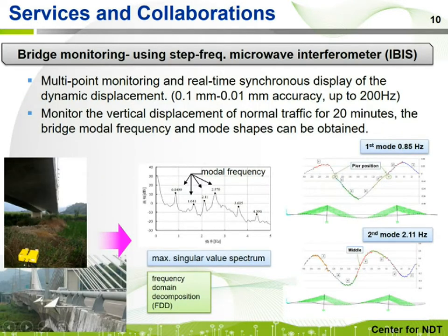An instrument called IBIS, which is a step frequency microwave interferometer, is used for bridge monitoring. IBIS can simultaneously measure the dynamic displacement of multiple points on the bridge deck. The accuracy is 0.1 mm to 0.01 mm, and the data acquisition frequency can be up to 200 Hz. So, if we monitor the vertical displacement of normal traffic for 20 minutes, the bridge modal frequency and the mode shape can be obtained.